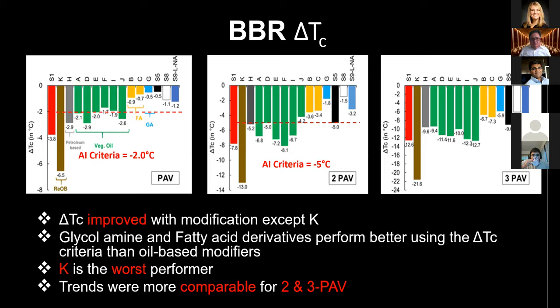As you move across the graph, you notice that all of the delta TC were improved with the modification except for K. The glycolamine and fatty acid derivatives performed better using the delta TC criteria than oil-based modifiers. K, again, was the worst performer and was included in this project, as a general rule, to ensure that we would capture the performance of REOB, something that is known in Illinois as not a successful modifier for our binders. If you notice, the trends were more comparable for 2 and 3 PAV aging, in that the aging at a single PAV does not necessarily capture the differentiation of the different modifiers adequately.